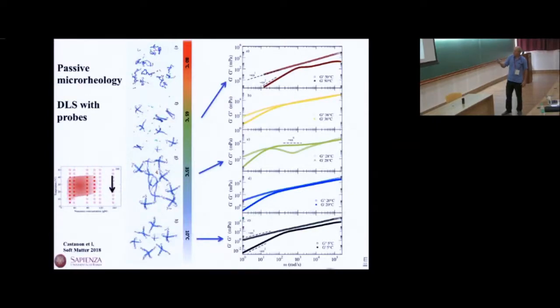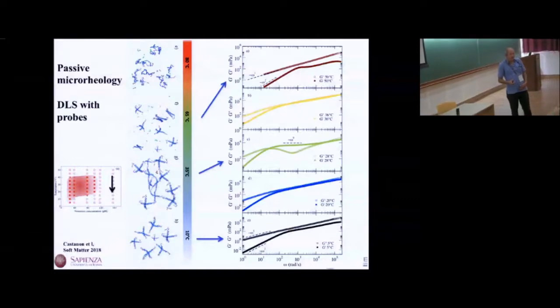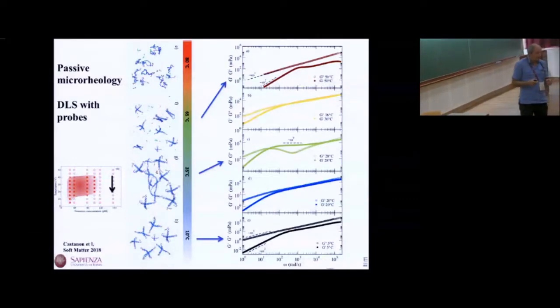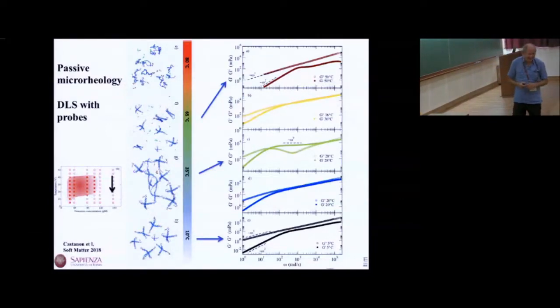Okay, we also want to prove the elastic properties. Okay, we want also to check the rheological properties of the samples. Of course, those samples are really tiny, 20 microliters, so there is not much that we can do macroscopically. So you have to put a probe in it. But the good thing is that if you put a colloidal particle, let's say 400, 500 nanometers, sufficiently large, the scattering of these particles kills the scattering of the DNA.